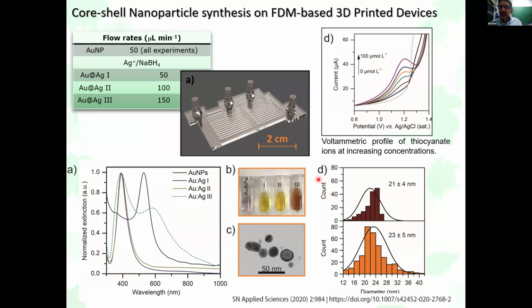Another application, we prepared some core shell nanoparticles, basically combining two mixers. So in one mixer, we introduce the gold nanoparticles. In another mixer, we have the silver source of metal that will be reduced over the gold. So you have a nanoparticle with the gold on the core and the silver on the shell. You can see the increase in the size of the particles. We can also see here kind of a new population of particles. And here the extinction coefficients of the particles synthesized.